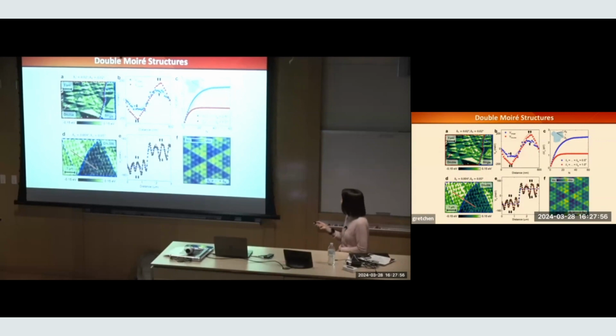So we just fold it one more time. If the two interfaces are the same in their twist angle, the potentials simply add to each other. Instead of 200 meV, we now have 400 meV with the 3 layers. And then you can extend it. You're not going to do this by hand, obviously. You need to figure out a way to stack multiple layers. Then the surface potential can be as deep as 2 eV. Right? You can trap a lot of things with a potential that's 2 eV deep.